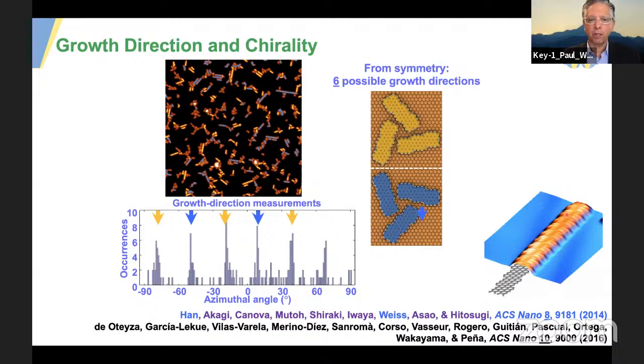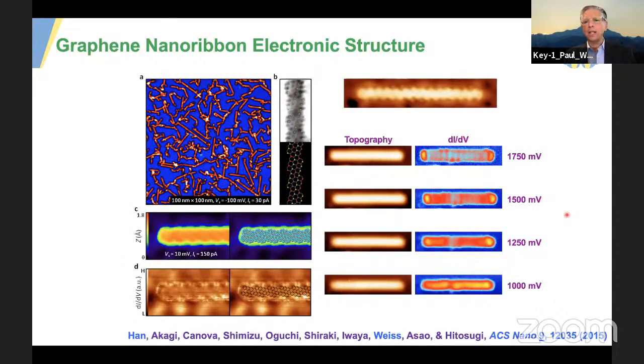Now, as I mentioned, we're able to do the spectroscopic imaging of these. We can vary the energy of the electrons that are either probing filled orbitals or empty orbitals, depending upon which way the bias voltage is placed. If we make our tip positive with respect to the substrate, then we measure the filled orbitals coming out of the graphene nanoribbon. We can do things like slide a bromine atom up to the edge of the graphene nanoribbon and break what's essentially a particle in a box into particles in two boxes by manipulating the molecular orbitals in that way.